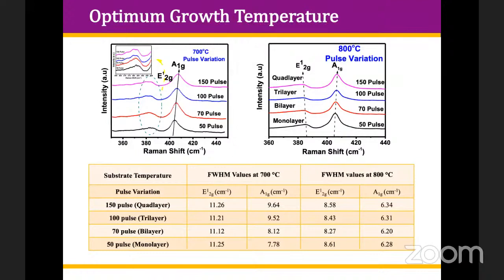And the deposition is over the entire 1 centimeter by 1 centimeter. Then we change the number of pulses, as we mentioned, from 50 pulses onwards. And you can see here, with 50 pulses we got the monolayer, 70 pulses we got the bilayer of MoS2, 100 pulses we got the trilayer, and 150 pulses we got the quad layer.